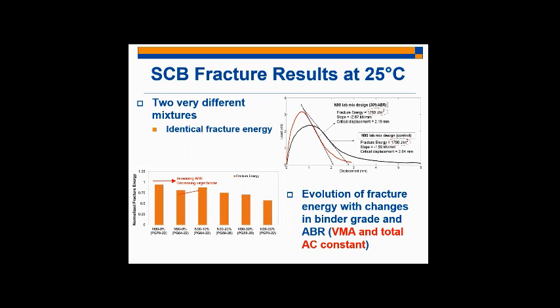One mixture, the red curve, which corresponds to the 30% ABR, is significantly more brittle. It's less ductile and is displaying a higher strength or peak load value. Where the control mix is displaying a more ductile, lower peak load, lower strength value. But if I look at the fracture energy, which is, again, the criteria typically used to screen mixtures or grade mixtures, the black curve displays a fracture energy of 1790 joules per meter squared. And the red curve displays a fracture energy of 1780 joules per meter squared.